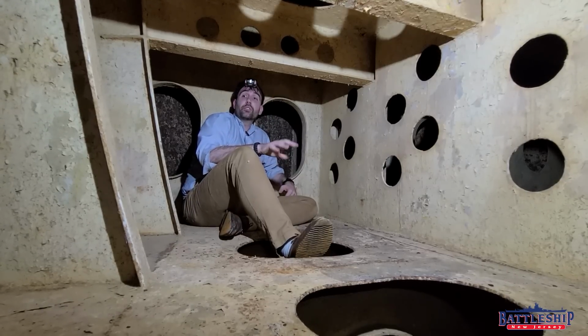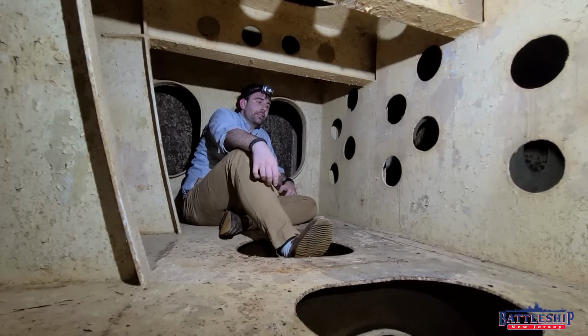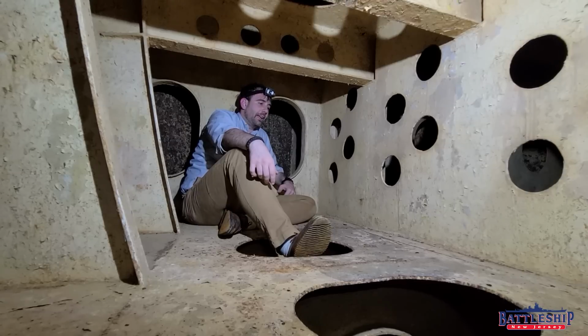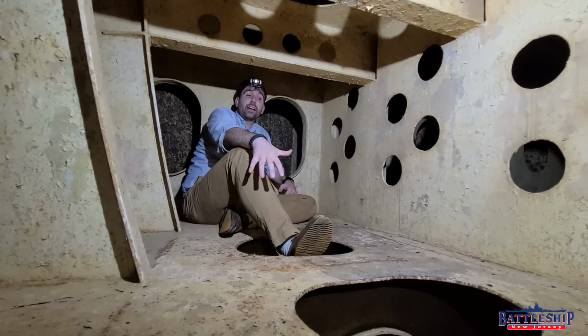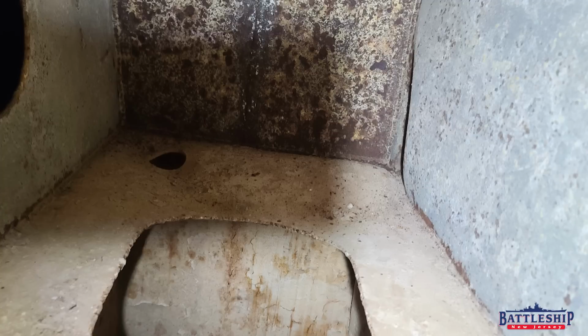So, the other known issue is the corrosion here at the extreme bow of the ship. And I only make it down here maybe once a quarter to inspect this and make sure that it's still dry and everything's still good. One thing that you notice when you come down here is that it's very little corrosion and a relatively fresh system of coatings in the entire peak tank. I get the impression that they came down and sprayed a relatively high build epoxy in these spaces right around when the ship was decommissioned.